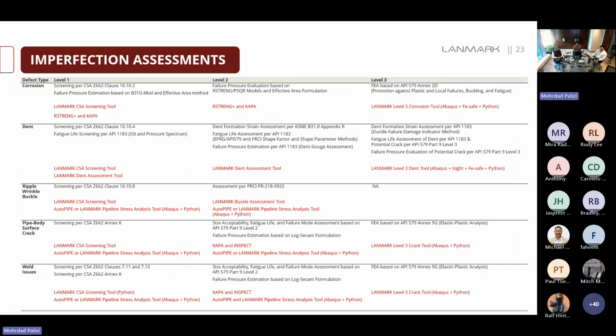So this slide here is showing this three-level approach that we are applying at Lanmark for doing assessment over different types of imperfections. As an example, for corrosion assessment, we start with CSA screening. Then we make progress to the ASME B31G modified formulation. If the data was available, we can also do an effective area method.